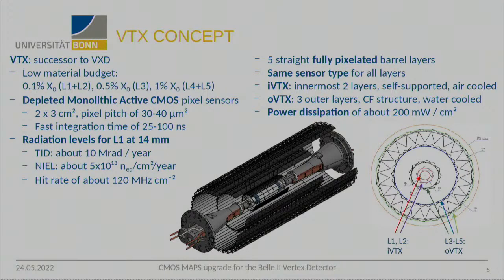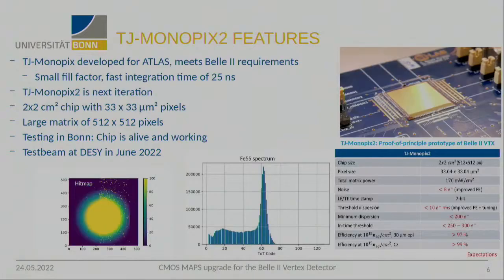We want to use 5 fully pixelated sensor layers and have the same sensor type for all layers instead of 2 different technologies as we currently use in the SVD. The 2 innermost layers will be self-supported and air-cooled, and the 3 outer layers will be supported by a carbon fiber structure and water-cooled, with overall power dissipation in the order of 200 milliwatts per square centimeter. This is a cut rendering and a 2D view of the detector.